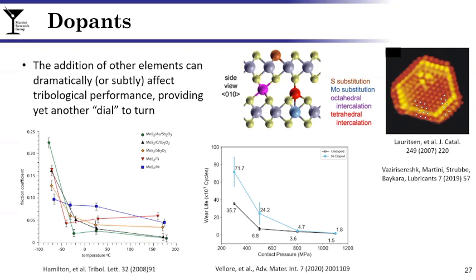In the middle figure, you're looking at wear life, so how long it took for coatings to fail. And in this study, we found that particularly for low contact pressures, the addition of a nickel dopant in very low concentrations dramatically increases the life. So this gives us, again, another dial to turn to change or tune tribological performance.